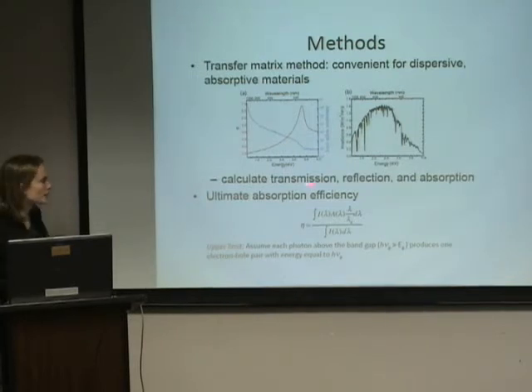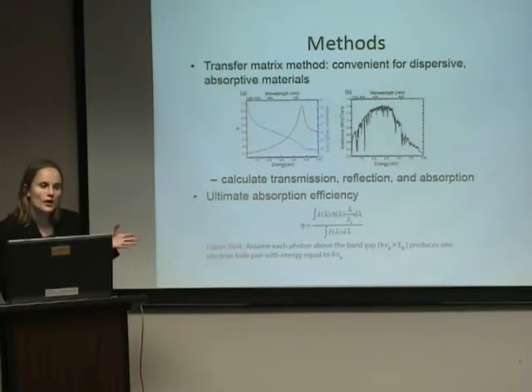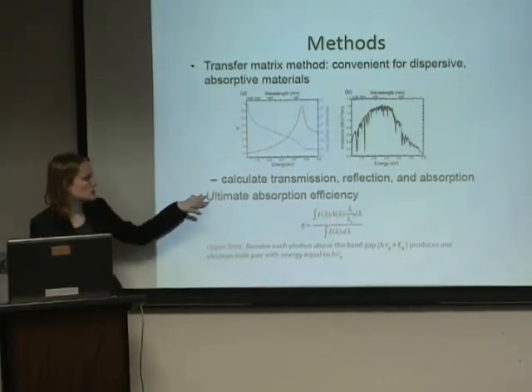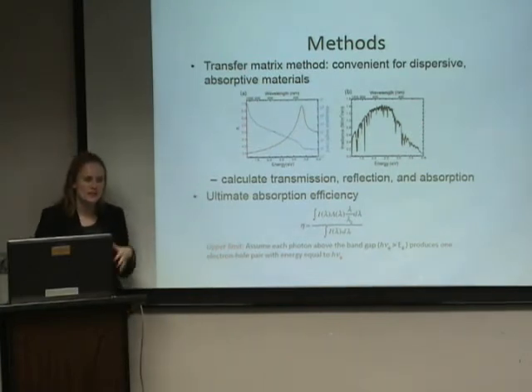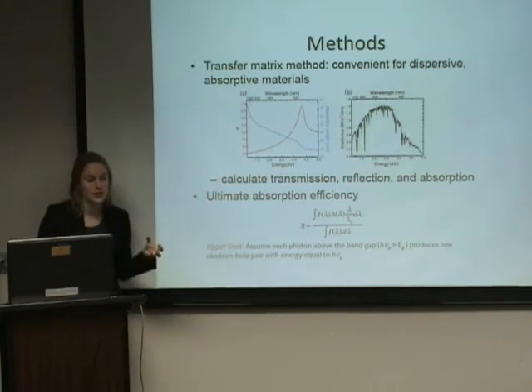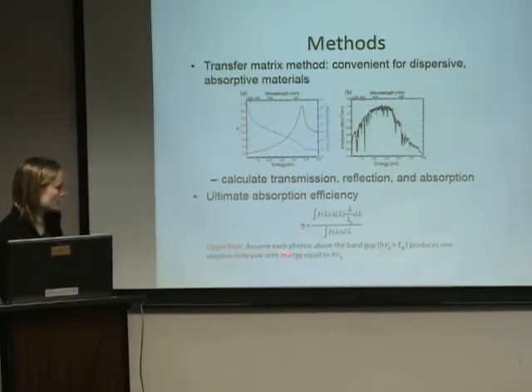So we took our structure and we calculated transmission, reflection, and absorption as a function of frequency, and calculated a number I'll call the absorption efficiency, which is a measure of how well this structure does across the whole solar range. So the absorption efficiency then is given in terms of an integral over the wavelength-dependent absorption, and it's weighted by the solar spectrum I. This corresponds to an upper limit on how well your cell can do. Remember, I said there are a lot of different effects. You have to absorb the light, convert it to carriers, and then collect them. This is an upper limit, assuming that every photon produces one electron-hole pair, and they all make it. They're all collected. So this is an upper bound on our structure.